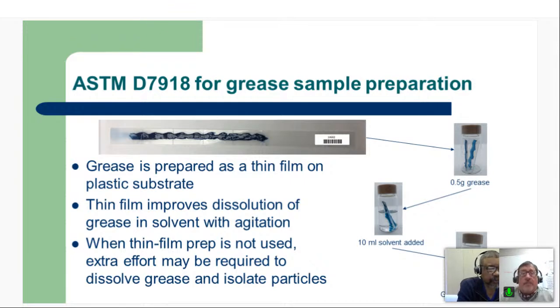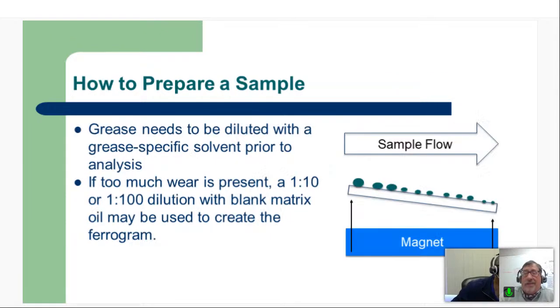If we don't have that as an option, if you're doing grease analysis and you're not using the grease thief analyzer, you're just taking a little clump of grease or whatever, there may need to be some extra effort there to dissolve the grease and to isolate those particles. And some of that's really going to be dependent on the chemistry of that grease. Some greases respond well to certain solvents, some do not, just based on their chemistries. And then also we see that as grease ages and gets degraded, it may be more difficult to get the grease out of the way for analytical ferrography. So we'll talk about that a little bit.